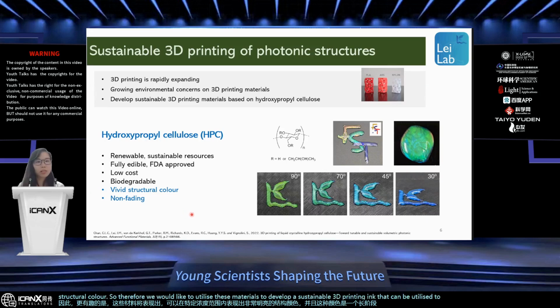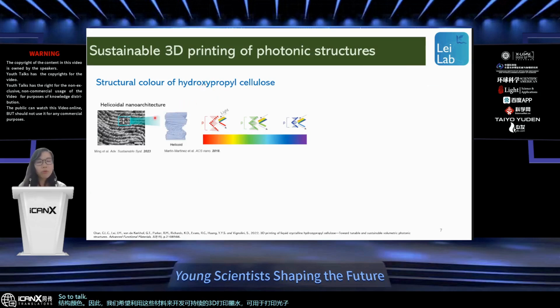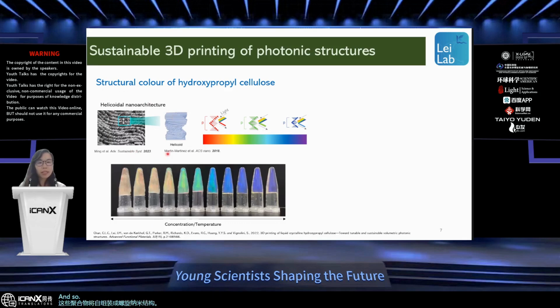that can be utilized to print photonic structures. To give more information about the structural color of hydroxypropyl cellulose, at specific concentrations of hydroxypropyl cellulose in a solution, this polymer will self-assemble into a helicoidal nanoarchitecture. Because of the existence of these helicoidal nanoarchitectures, when light shines on this polymer, a specific wavelength of the light will be reflected from the polymer solution. Therefore, we can tune the color by changing the concentration and the temperature of the